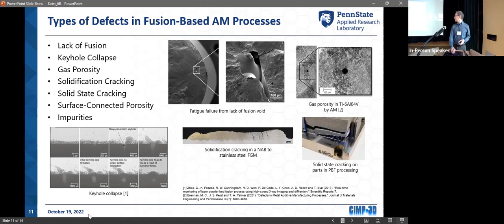Another is keyhole collapse. What happens is that when you run high powers, you can develop a keyhole condition, which is basically a deep trench of a melt pool. If you're not careful, that melt pool can collapse, creating a pore. As it solidifies, metal wants to shrink, and that pore forms in that area. Another thing is gas porosity.